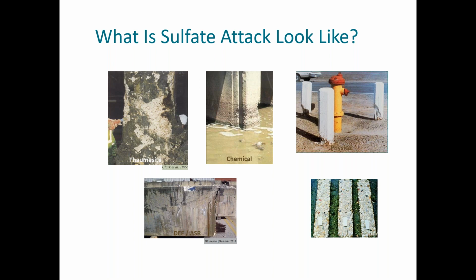But what is agreed upon is that this is a phenomenon that only happens when concrete is initially cured at very high temperatures. It affects the sulfate phases within the cement and causes a formation of ettringite at a later age, when the concrete, or the paste, is not capable of accommodating this increase in volume, and so you see these types of cracks. And of course, you can understand that once you have cracks in concrete, you can have all kinds of other types of deterioration problems, whether it be corrosion of steel or ASR or anything else that might cause degradation to concrete.